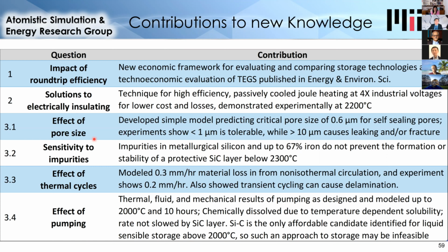I investigated the effect of pore size at temperatures up to 2300 degrees Celsius and showed that the critical pore size is somewhere between 1 and 10 microns. I investigated the effect of impurities, showing that metallurgical grade silicon can be contained successfully at 2300 Celsius and up to 2/3 iron can be used.